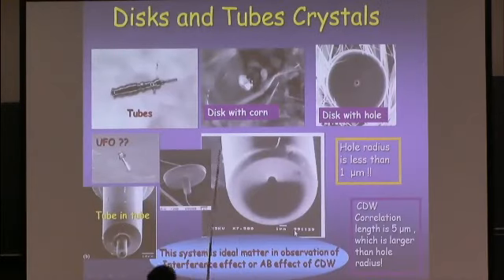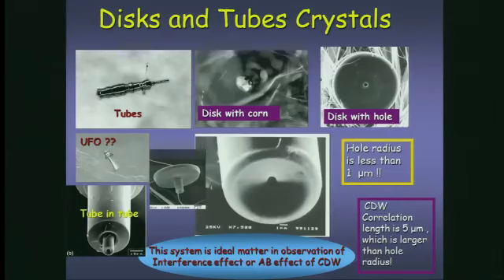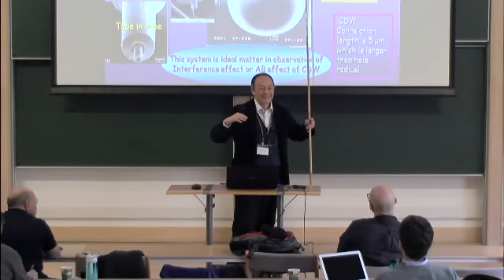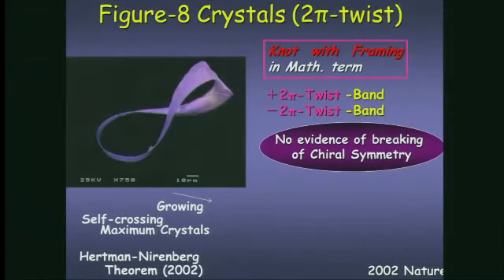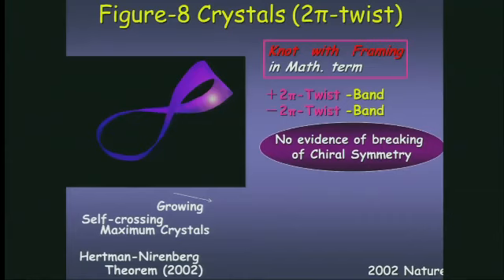Another type of ring, we obtain tubes, disc with cone, disc with hole, UFO type, another UFO type, tube in tube, and ring crystal. The hole radius is less than 1 micrometer. It means that this system is an ideal matter for observation of the interference effect, the AB effect, of CDW. The CDW correlation length is about 5 micrometers, which is larger than the hole radius. Later, I will show you. Charge density wave. Next, we obtained figure 8 crystals, like this figure.